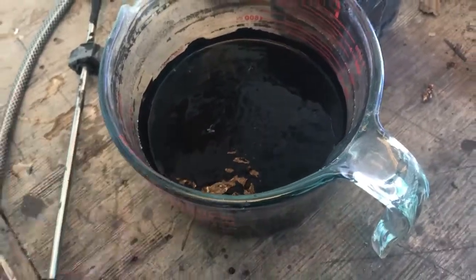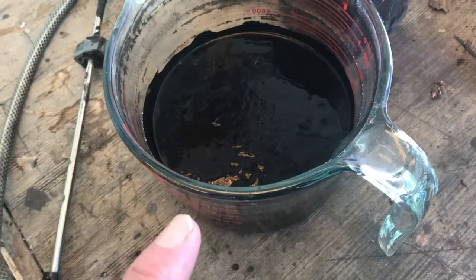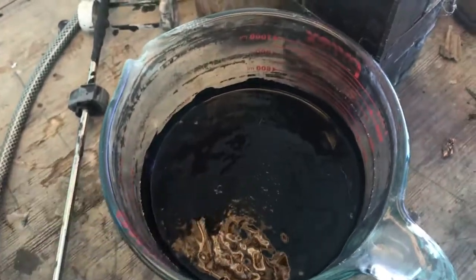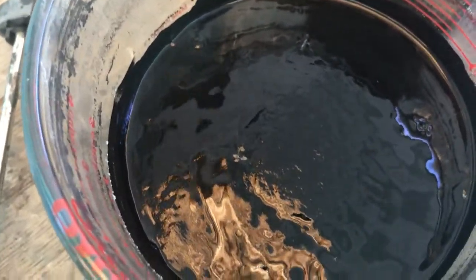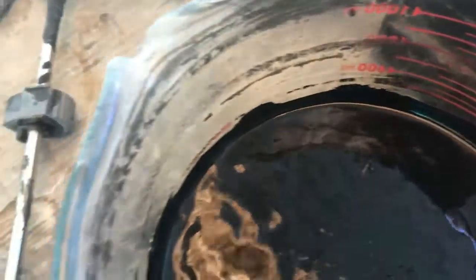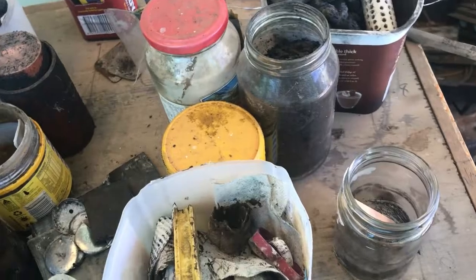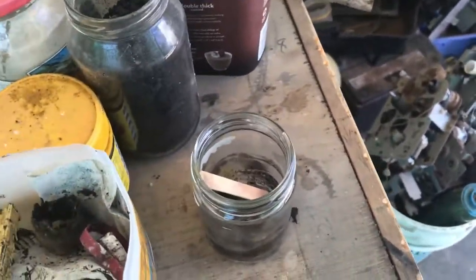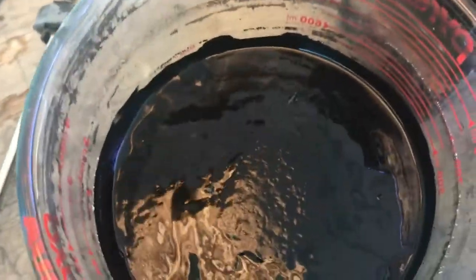Oh, and also after the nickel hydroxide was made, I put 100 mils of bleach into the solution and had it on the stirrer for a while, which forms the nickel oxyhydroxide. I had a little test batch, which I thought was a real lot, but it's only a little fraction of that stuff. It dries right out to nothing. But this one was the contaminated stuff, which I did that electroplating in, which failed because it wasn't nickel. So waiting for that to dry.